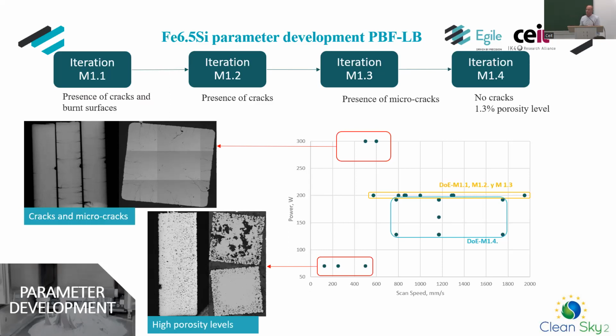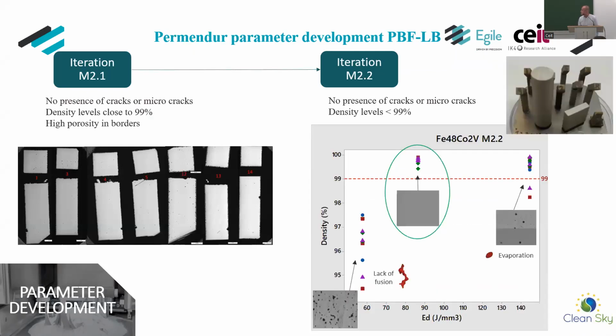Until the third iteration, we weren't able to avoid these cracks. On the last iteration, we were able to do it, but we had 1.3% porosity on our last attempt. So we concluded that this wasn't suitable for the application. The next material we worked with was Permendur, where only two iterations needed to be done.